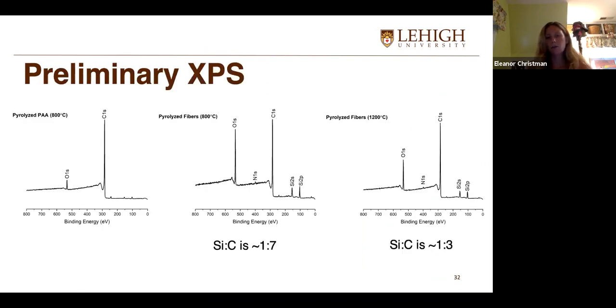And here I have some preliminary XPS data, which I've just plotted and I'm still working on. I have the pyrolyzed PAA fibers, the pyrolyzed ceramic fibers at 800, and the pyrolyzed ceramic fibers at 1200. Similar to the powder, you can see that the silicon to carbon ratio is increasing. So the amount of free carbon is again decreasing as the pyrolysis temperature increases, which is what we expected and is consistent with our data from the powder.